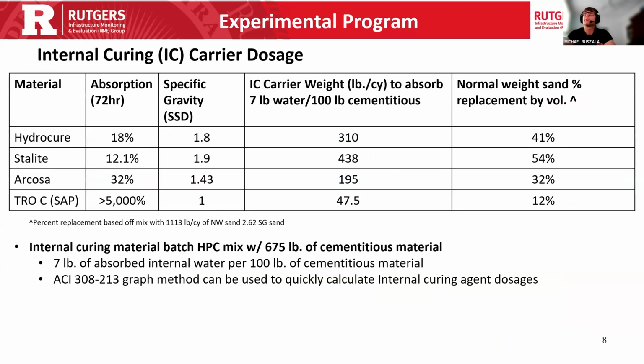So regarding the dosages, there's a lot of discussion on what the proper dosage should be. Typically, that's resolved itself. It's mostly agreed upon that for the best benefit, you do 7 pounds of internally absorbed water per 100 pounds of cementitious material. So it's pretty straightforward to modify existing HPC formulations. So given a typical NJDOT HPC mix, 675 pounds of cementitious material per cubic yard, you can see the required dosages using these different materials.